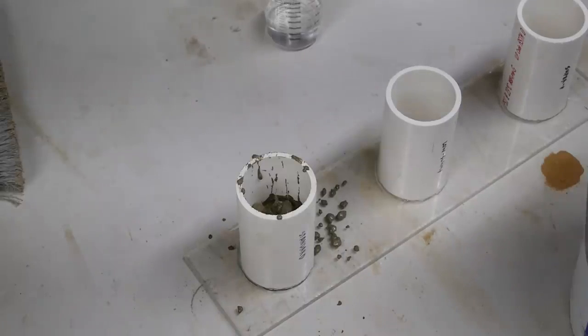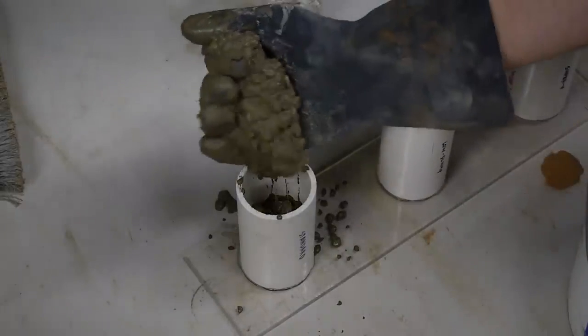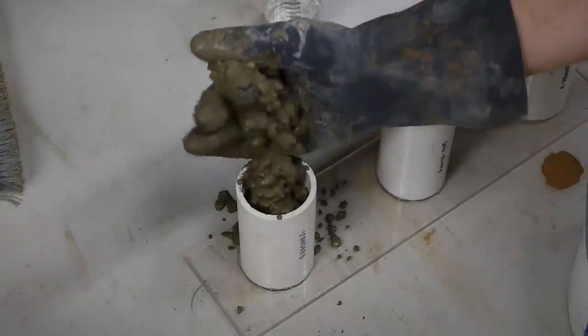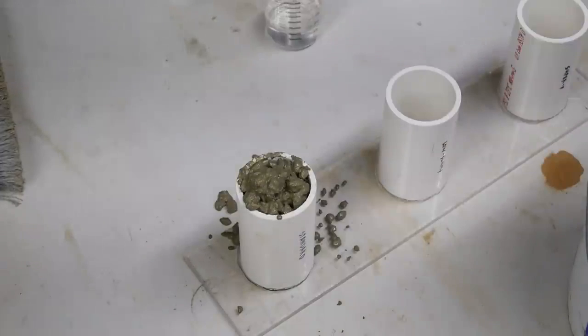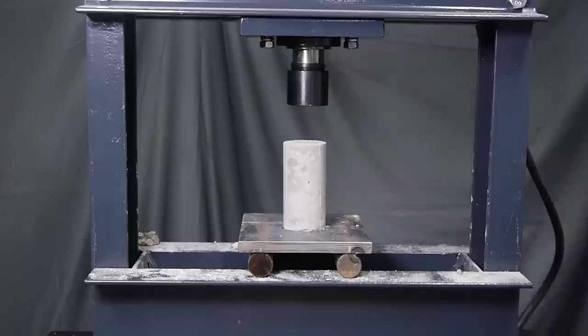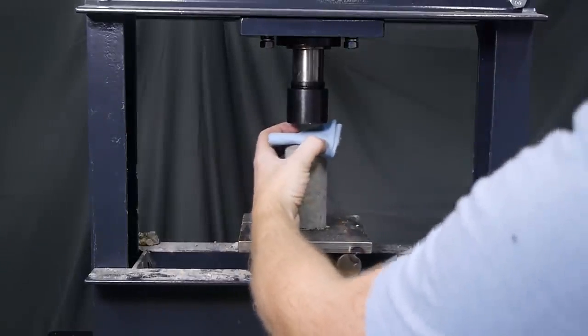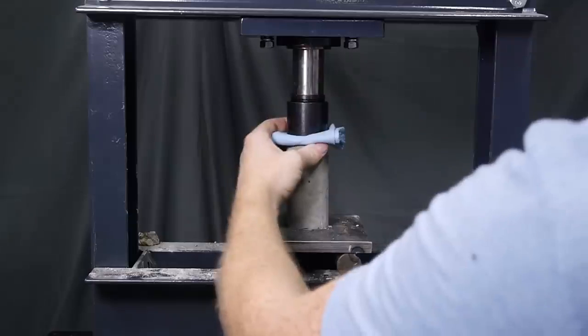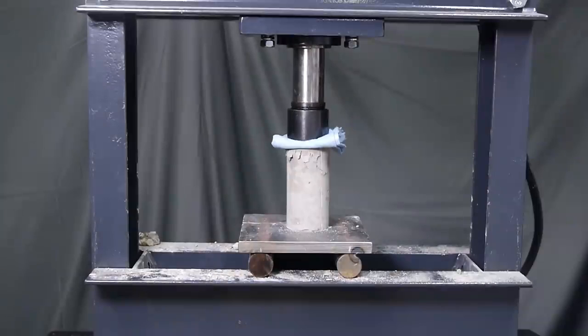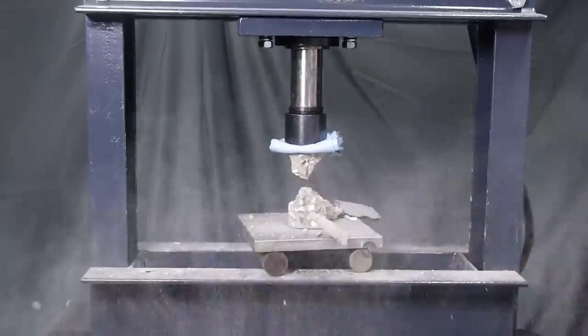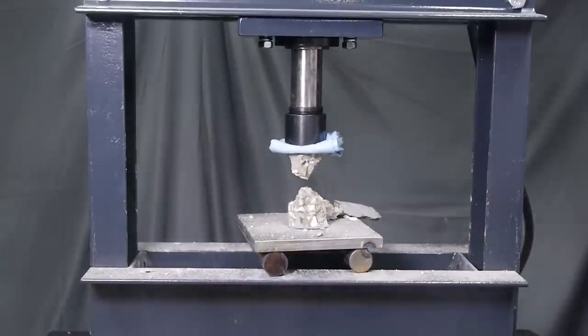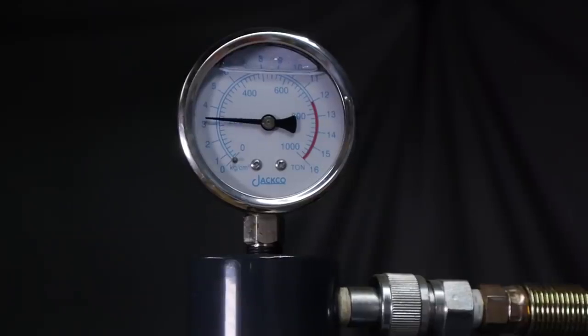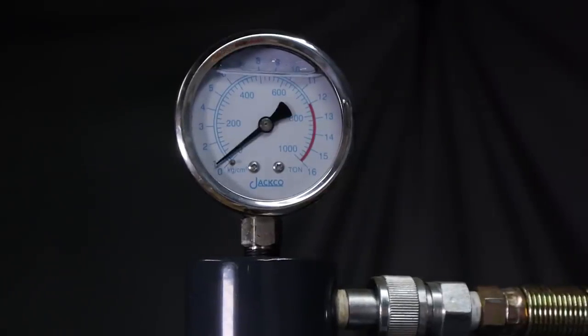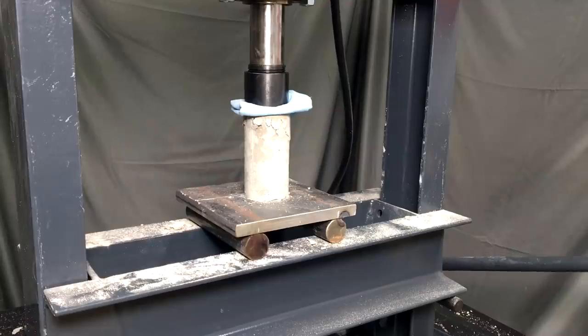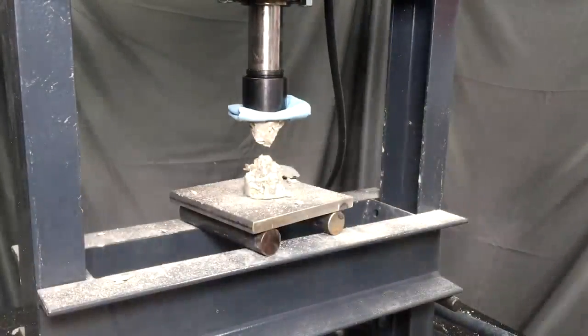In this first one, I'm using the recommended amount of water for a standard mix. Notice how the concrete flows nicely into the mold without much need for agitation or compaction. After a week of curing, I put the sample under the hydraulic press to see how much pressure it can withstand before breaking. This is a fairly standard test for concrete strength, but I'm not running a testing lab in my garage, so take these numbers with a grain of salt. The sample breaks at around 2000 psi, or 14 megapascals, a relatively average compressive strength for 7-day-old concrete.